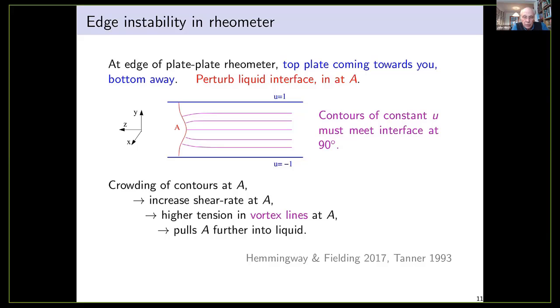To measure viscosities, you often have a circular plate, and you put a blob of liquid on it, then you put another circular plate on top, and you rotate the top plate and measure the torque to measure the viscosity of the fluid. And sometimes, depending on the viscoelastic nature of the liquid, it won't stay between the two plates, it just flies out. And it does it not through inertia, but through non-Newtonian stress effects. So this is looking at that phenomenon of the fluid flying out from between the two rotating discs.